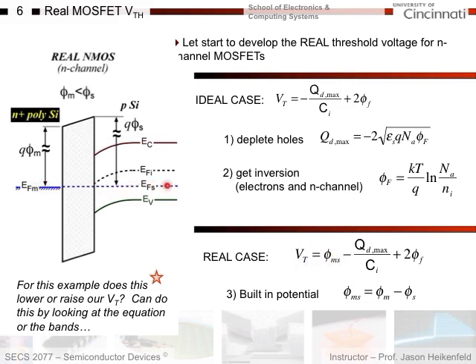When the Fermi level is lined up, you could see that it's helping me start to bend the bands down. And we said that when we turned a MOSFET on, if it's an n-channel device, we had to bend these bands down here to basically get the surface potential to get 2 phi sub f, right? Well, you can clearly see that when these line up, it gives you a little bit of a head start. So this lowers our threshold voltage, which again should make sense given that this is a negative sign here in the threshold voltage equation. And so I have my ideal case, which is depletion and 2 phi sub f. And now for the real case, I'm adding in addition to those two, the phi sub ms, the difference in.